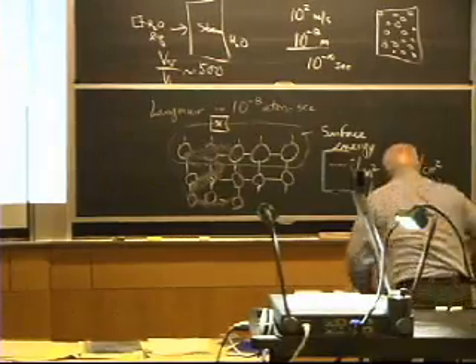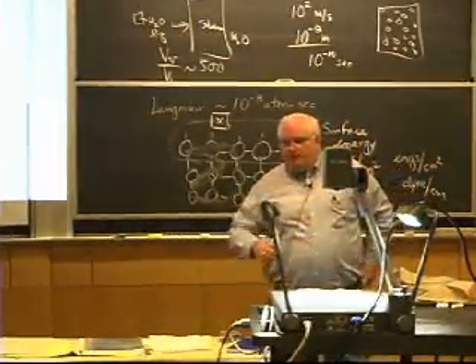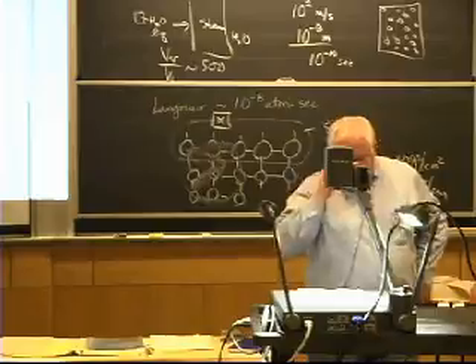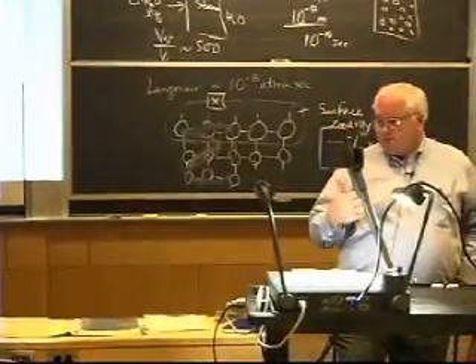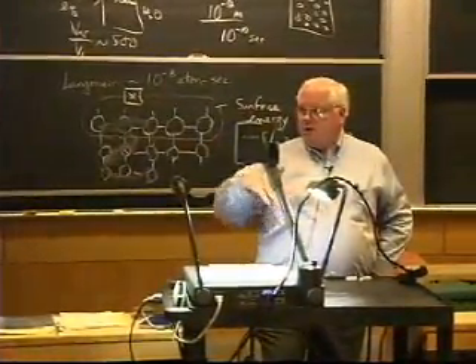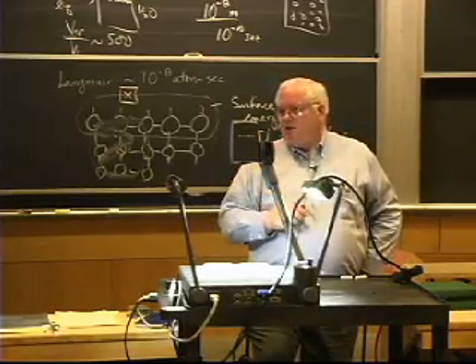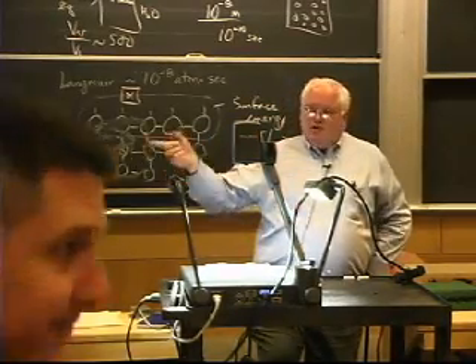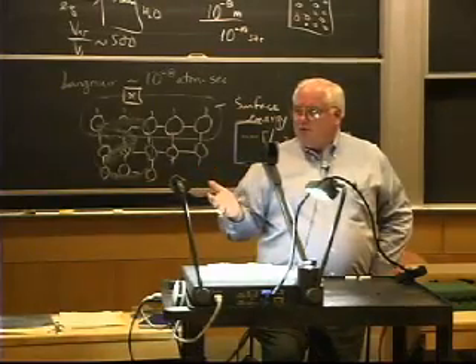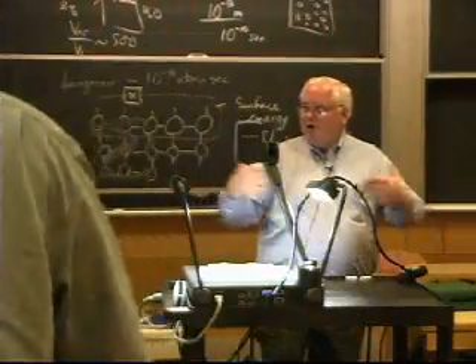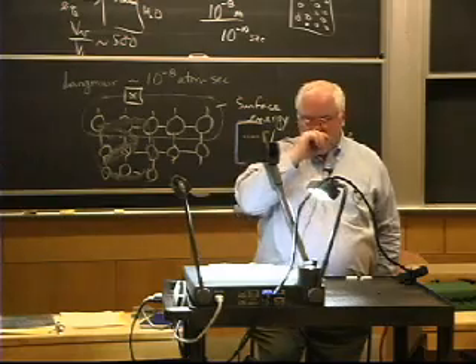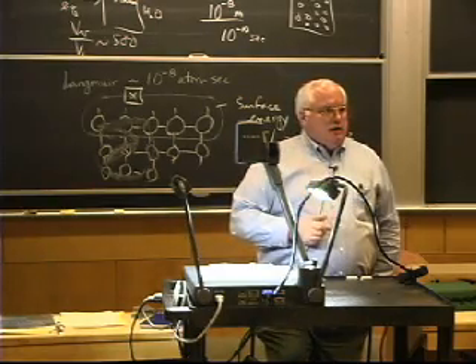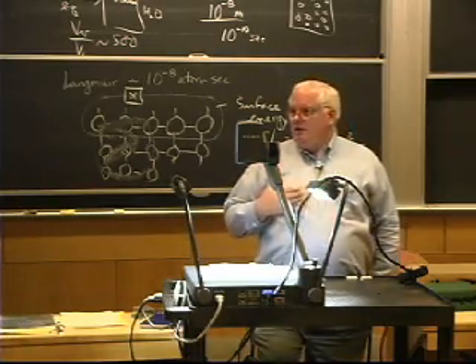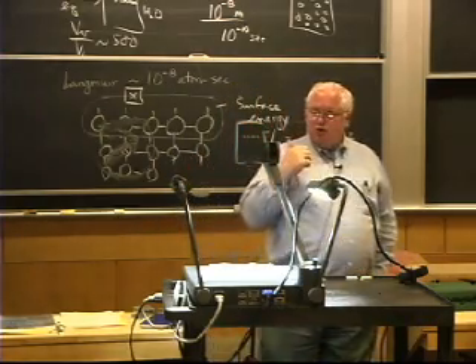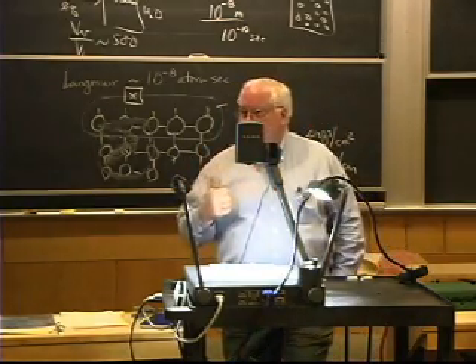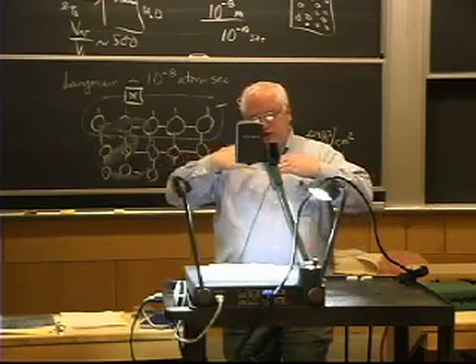The process is, they used to have 20-pound rods of tantalum that come out of the way that you make the tantalum alloys. And they have a machine that will roll up 500-pound spools of wire. Well, they had to have a way to weld the 20-pound pieces together. And that's how they do it, okay? It's just cold welding, and you've gotten rid of both surface contamination, and you solve the problem of surface roughness because of this interfacial sliding.